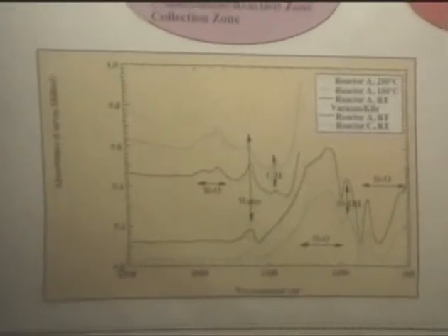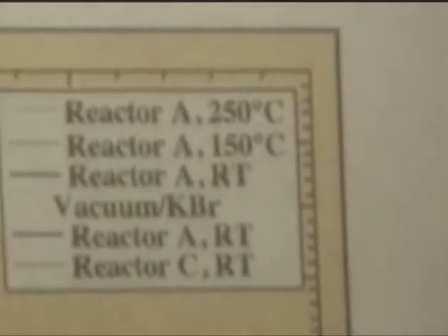Okay, they have IR curves from this kind of material. We're looking at some organic content, significant hydroxyl and water content, because water is one of the vapors in the materials. From these curves, you can also tell with a mixed oxide how there's a peak that's associated with the Si-O-Ti bond, so you can quantify the amount of that.